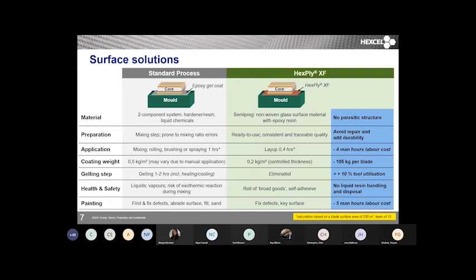And it has a very light preparation. One of the built-in features of a gel coat is you apply a reasonably thick layer, maybe 400 microns, so that you can abrade it quite roughly to get the keyed paint surface ready. Whereas with XF, you just need a wash and a Scotch Brighting, and then you're ready to start the paint process.